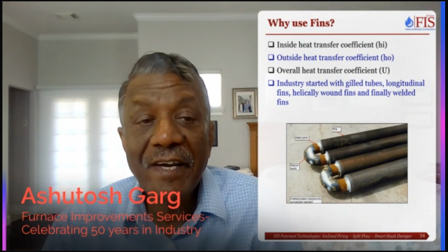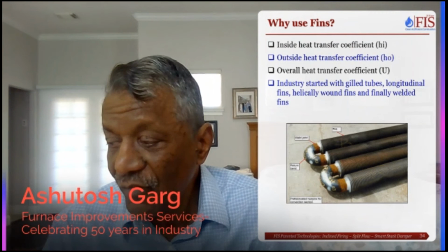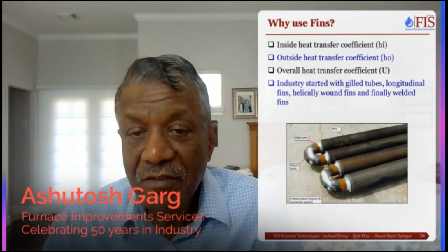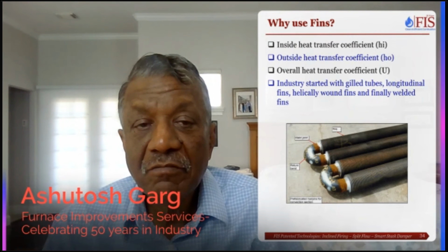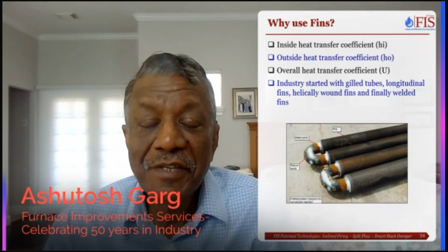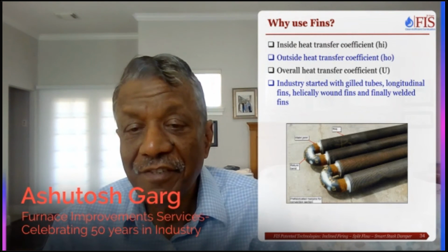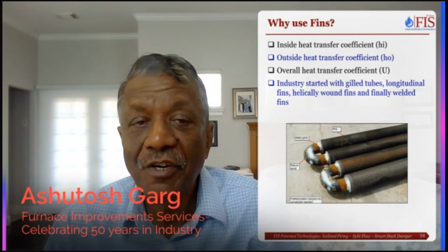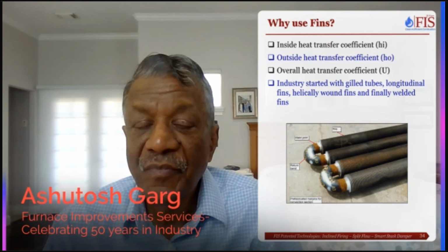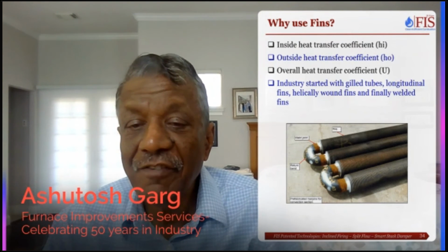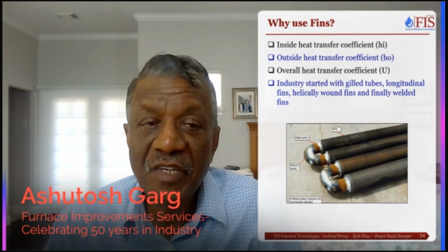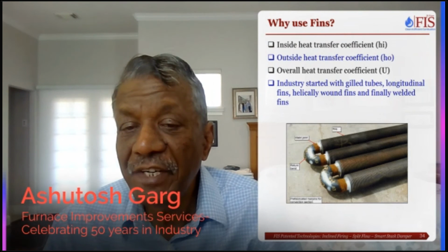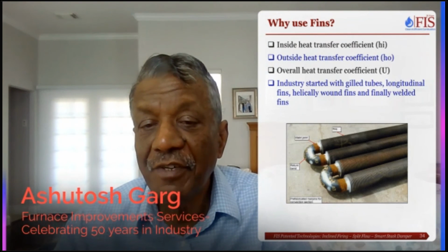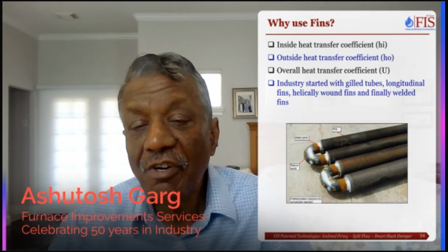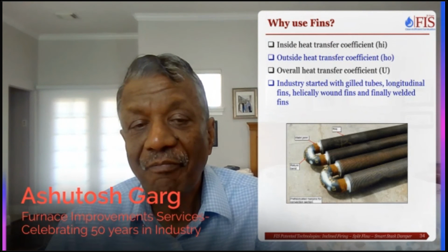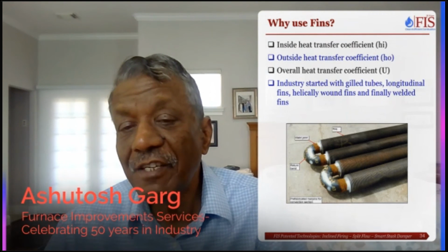So the question comes, why use fins actually? So I want to tell you something, which is in fired heaters, it is the flue gas side which is controlling the heat transfer surface or heat transfer coefficient, whether it's in the radiant section or in the convection section. Inside heat transfer coefficient could be anywhere between 100 to as high as 1000. Outside heat transfer coefficient could be between 5 to 10. So if you look at the two heat transfers, 5 versus 500, overall heat transfer coefficient will be closer to 5.